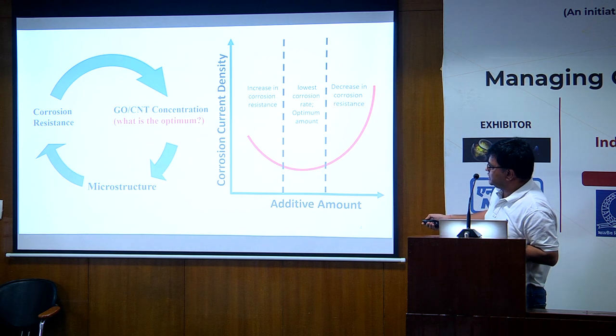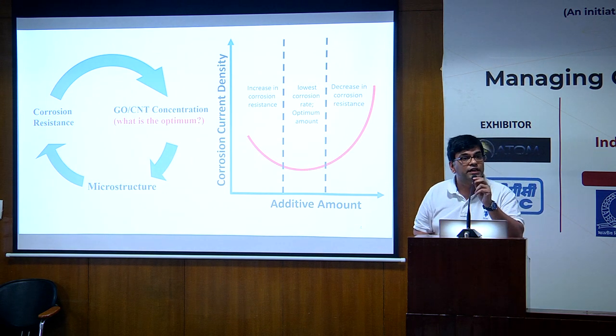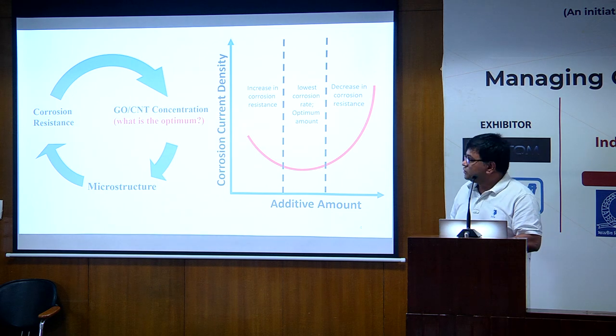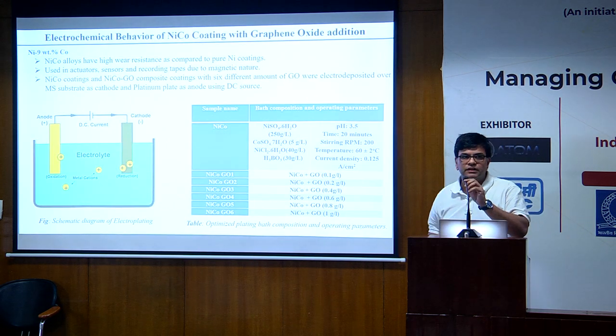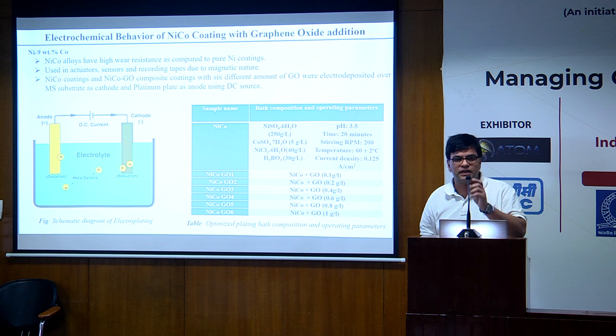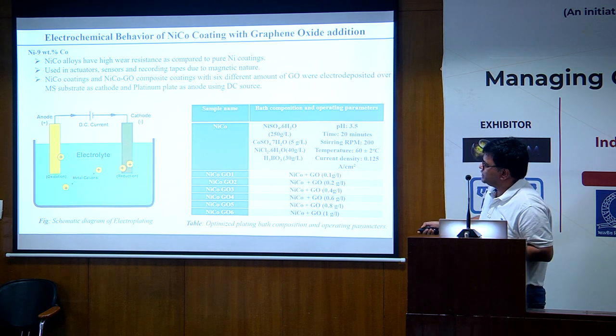But in the range starting from here to here, something important happens, and that is the change in the texture of the coating itself. I'll show you that. I'll take the example of a nickel cobalt coating, and as you can see, we use the electrodeposition method to deposit this coating.